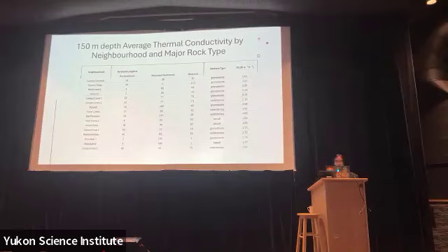The neighborhood that came up on top was Canyon Crescent and Ravens Ridge, with 2.6 to 2.5 watts per meter Kelvin. This is where the bedrock is very close to the surface. And then the losers of my, well, they're not losers, Golden Horn, the area with the sedimentary rock, is looking at 1.64 watts per meter Kelvin.